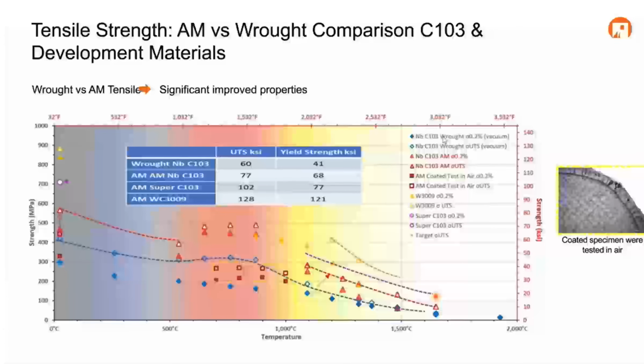Going from top to bottom on the key here, the blue diamonds are the wrought material, tested in vacuum, for ultimate tensile strength and yield strength. Then we have the AM C103 material also tested in vacuum, shown as the red diamonds. We have some AM material in the red squares that was tested in atmosphere, but was coated.